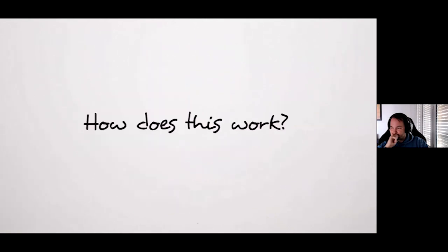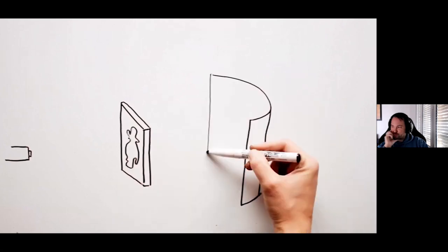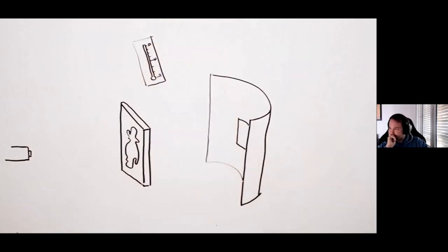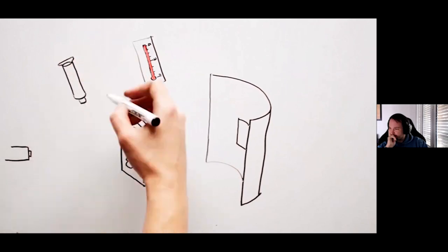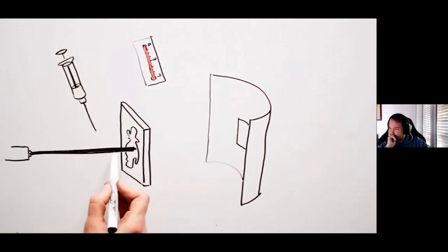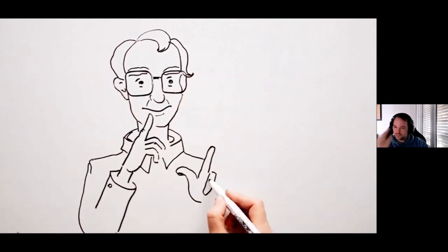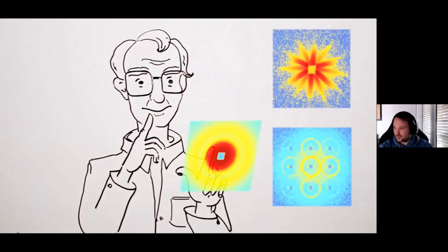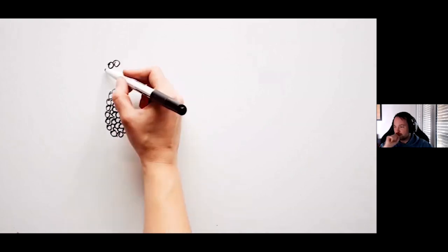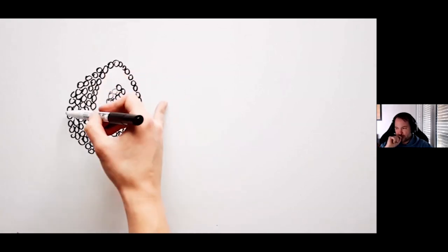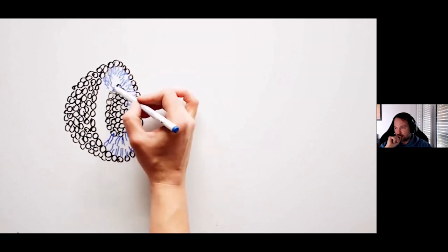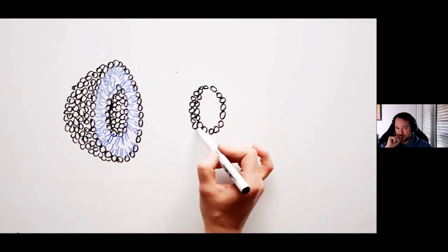How does this work? A product sample is placed in a SANS instrument. The instrument is temperature controlled, and an injection system allows blending if necessary. A beam of neutrons is directed at the sample. The matter of the shampoo deflects some neutrons from their trajectory. A large detector records the position of these deflected neutrons. The result is curious figures, which the experts will analyze. This measurement makes it possible to determine the shapes, sizes, and spatial organization of the scatters of structures in your shampoo, ranging from 1 nanometer to 1/10th of a micron.